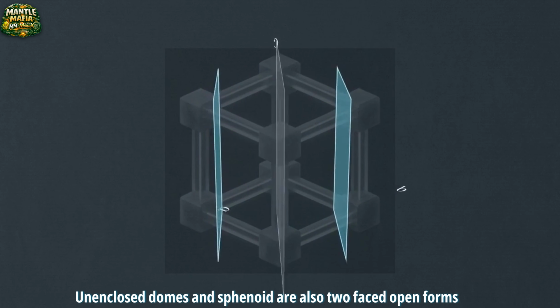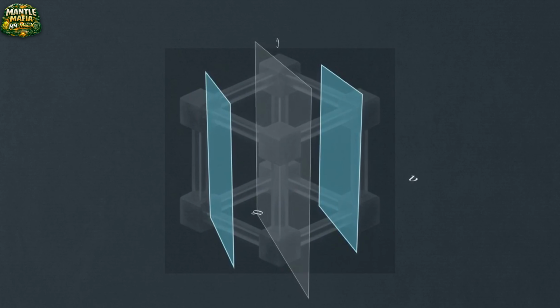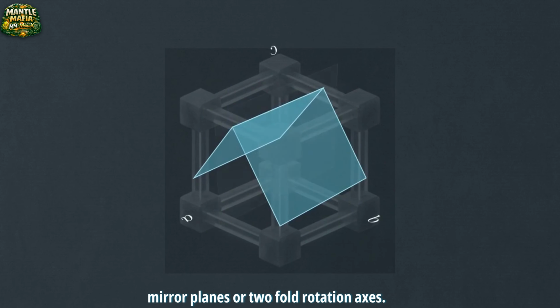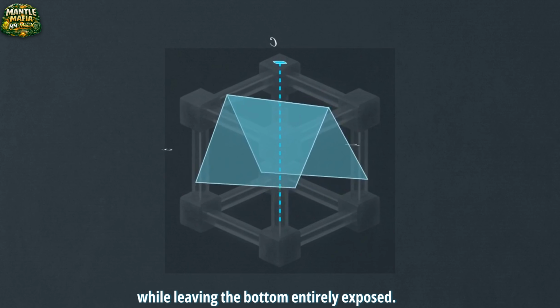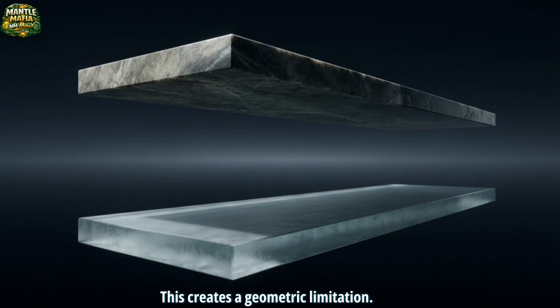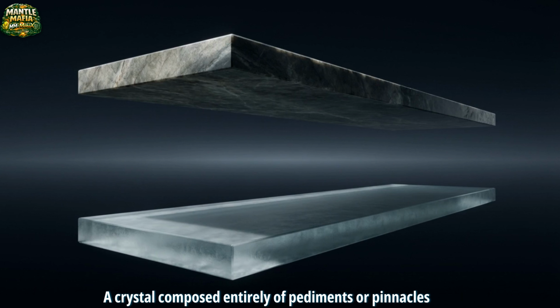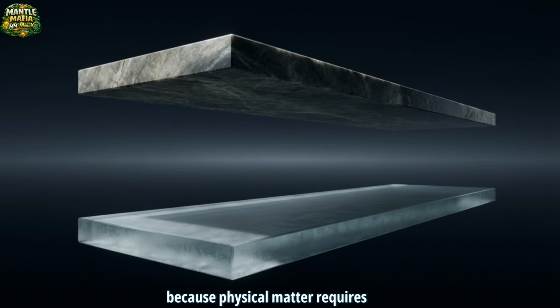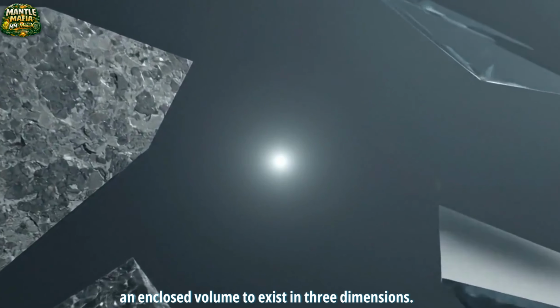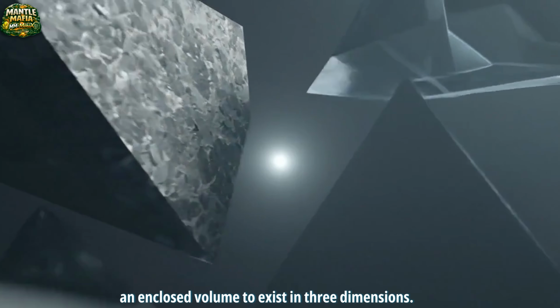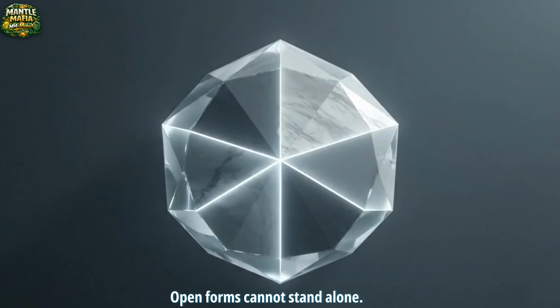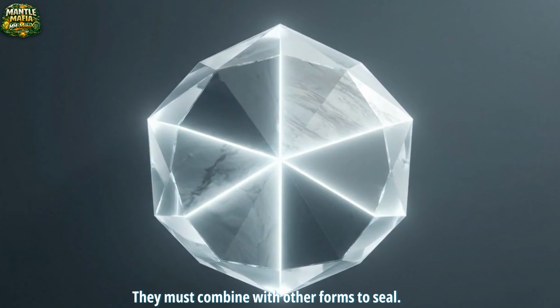Domes and sphenoids are also two-faced open forms. Driven by different intersecting mirror planes or twofold rotation axes, their faces intersect at the top while leaving the bottom entirely exposed. This creates a geometric limitation. A crystal composed entirely of pedions or pinacoids cannot exist without intersecting supplementary forms. Because physical matter requires an enclosed volume to exist in 3 dimensions, open forms cannot stand alone. They must combine with other forms to seal.